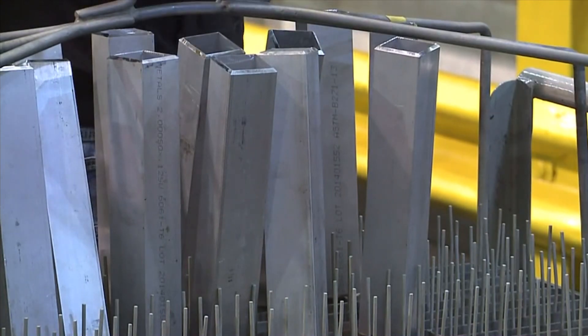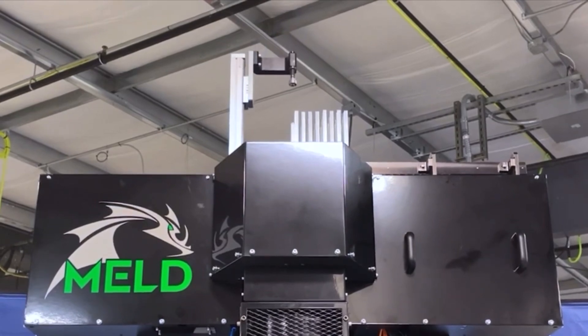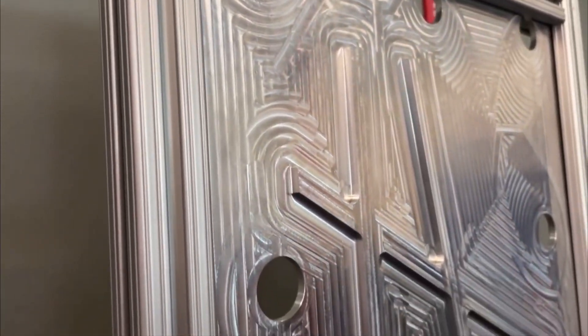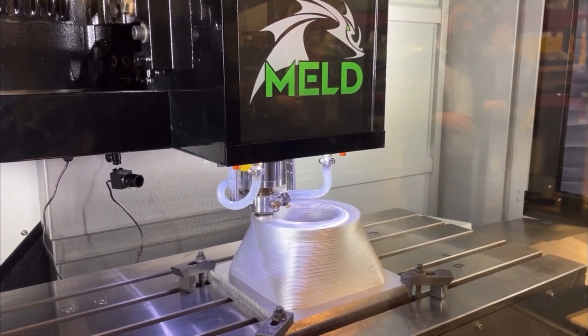The stock material used are rectangular bars fed through the top of a rotating printhead at a rate of 2 feet per minute. Because the metal is not melted and cooled, the deposition rate is much faster and is resistant to warping as the part is printed. And because the machine applies metal in an open-air environment, this process can be used to repair existing parts.